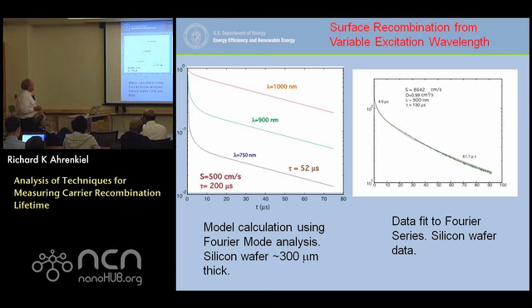They recombine very quickly, and so we see a very sharp initial dip, and then a leveling off as the carrier profile flattens in the bulk of the material. We can start with that by putting in very weakly absorbed light, which puts in a flat profile, and we see this kind of decay. So by changing the wavelength, we can see the surface recombination effect very markedly. In fact, I like using a YAG and double YAG, 532 and 1064, that go from down here to up here, to see if surface recombination is a factor.